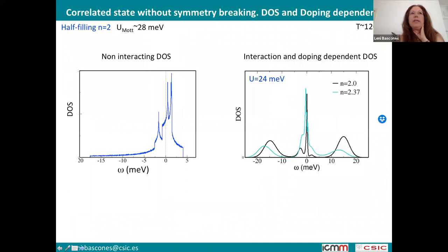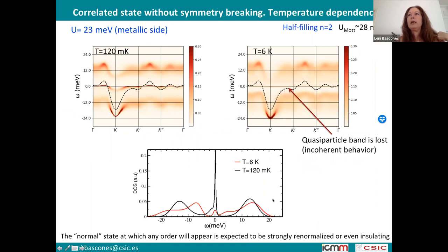So something that we expect is that our density of states is going to be doping dependent. For example, it's not going to be a rigid band shift. And if we are very close to the Mott transition, we will also see some temperature dependence. In fact, with temperature, this band is expected to be more incoherent. So if this kind of description applies to the system, we expect a normal state which, even if still metallic, is going to be modified.